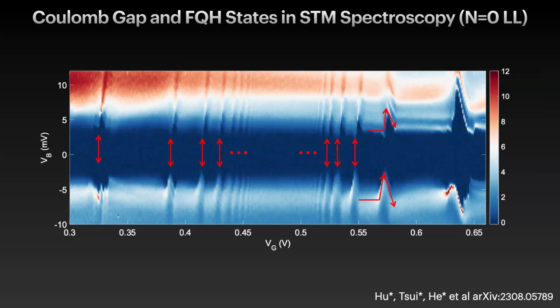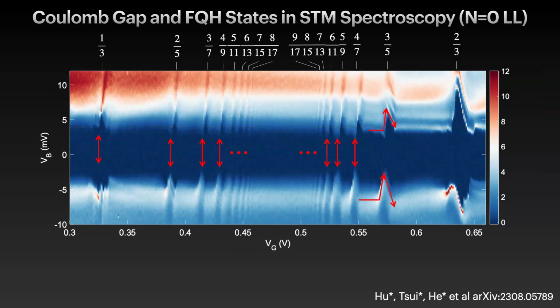And what you see are all these jagged features in the data. So these are all the fractional quantum Hall states. And as you tune your gate voltage, field is constant, 14 Tesla. As you tune your gate voltage, you're going through the different sequence, and you go in and out of incompressible states. And when you go in and out of these incompressible states, essentially you see an additional energy that goes into the tunneling to get an electron in and out of the sample, which reflects the presence of the incompressible fractional quantum Hall state.